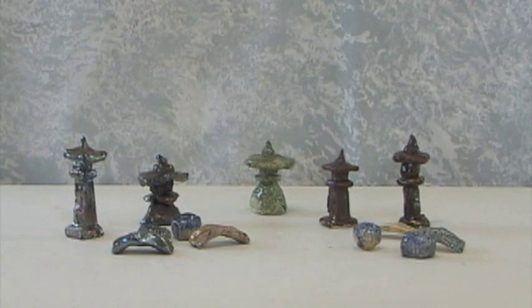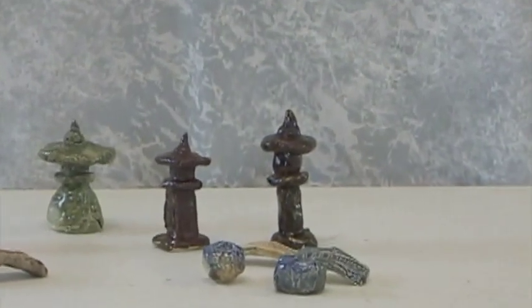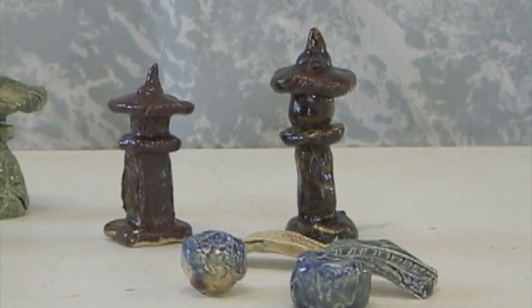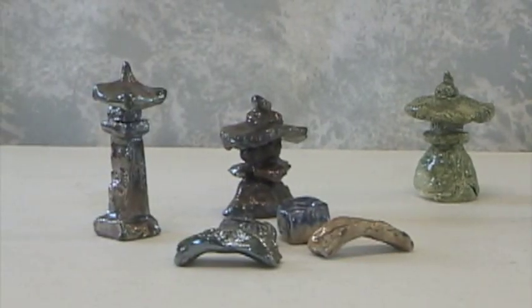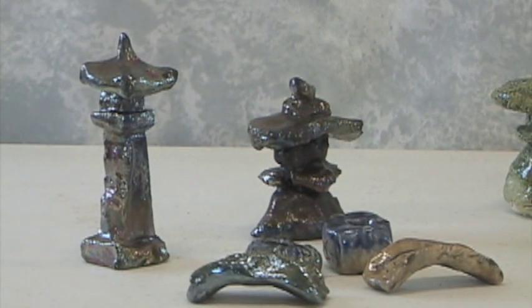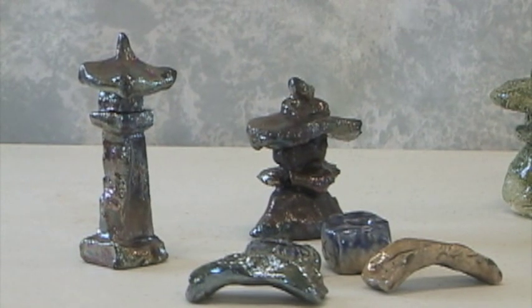These are the results as I took them out of the kiln and cleaned them up. This side is the group that stayed in the kiln and cooled naturally. This group came out of the kiln when it was still very hot, went into the chamber, caught fire with the shredded newspaper, and the cover was put on to cut out the oxygen. This process is called reduction. When there is no oxygen, the copper metal in the glaze turns metallic — that's the result of reduction.